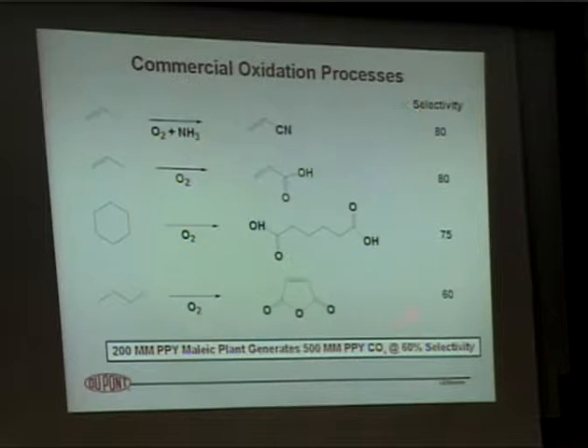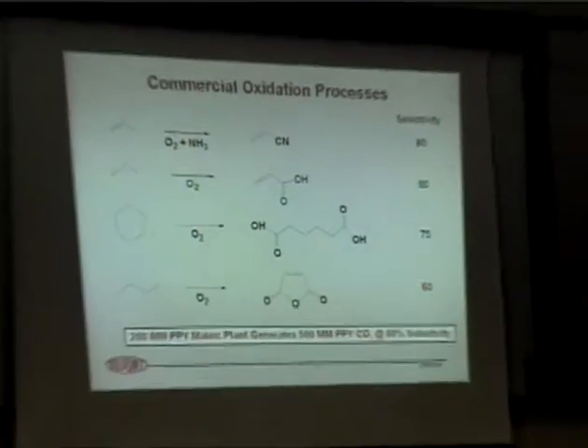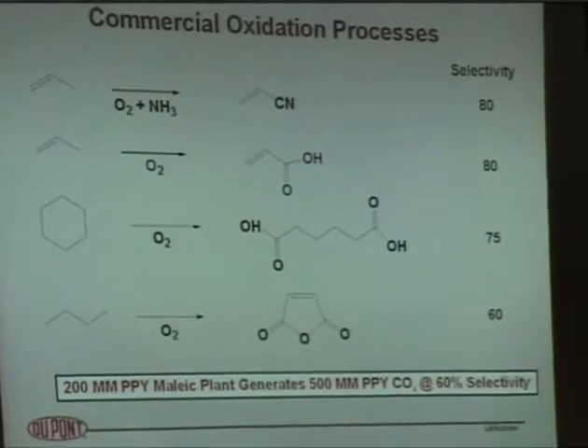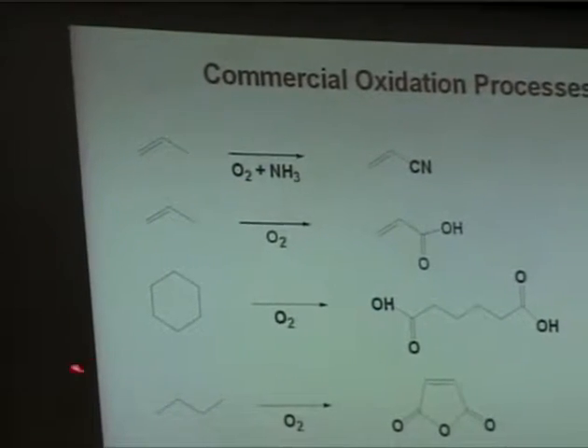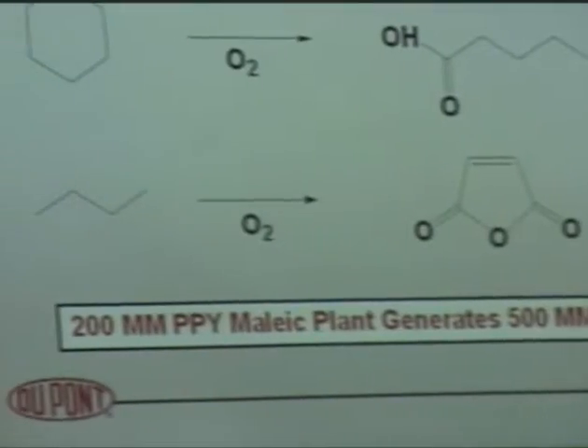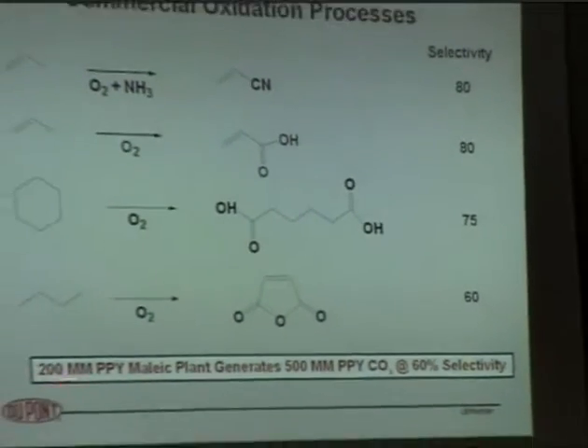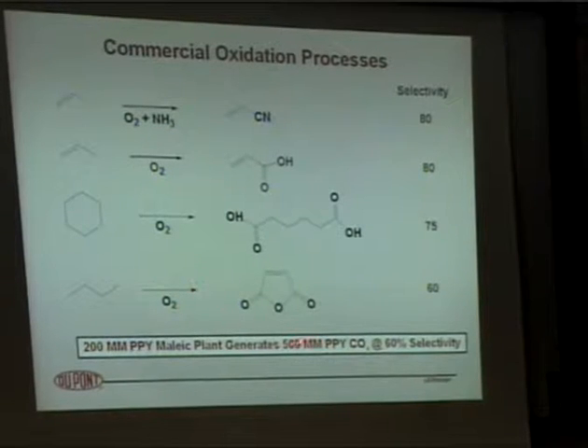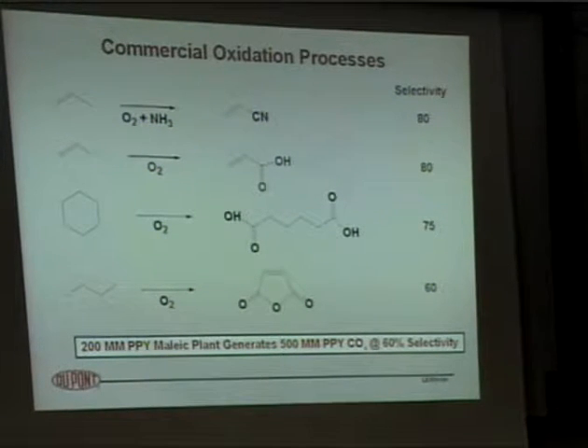Some of the selectivities of commercial oxidation processes are shown here. They're not very selective generally. This is one of the least selective of all catalytic processes. And take, for example, the bottom reaction here, the oxidation of butane to maleic anhydride. Operated on a very large scale commercially, 60% selectivity on the average. Well, a plant that makes 200 million pounds a year of maleic anhydride actually makes 500 million pounds a year of carbon dioxide. So you're really running a carbon dioxide plant with maleic anhydride as a byproduct in this process. But that's typical of what happens in many of these oxidation processes where you make carbon dioxide. So you can see there 500 million pounds a year out of a single maleic anhydride plant.